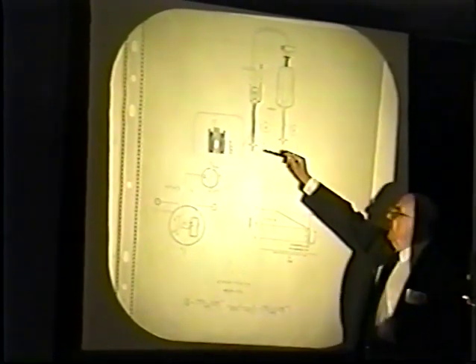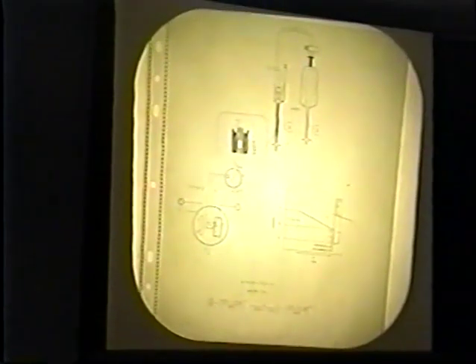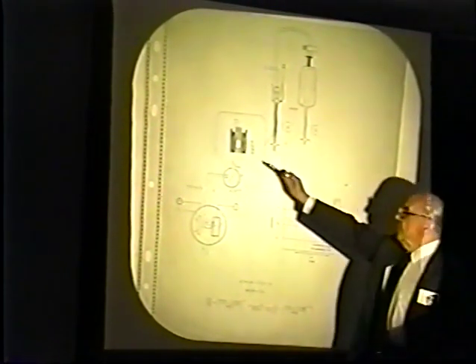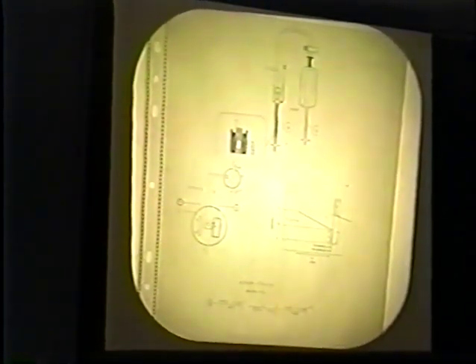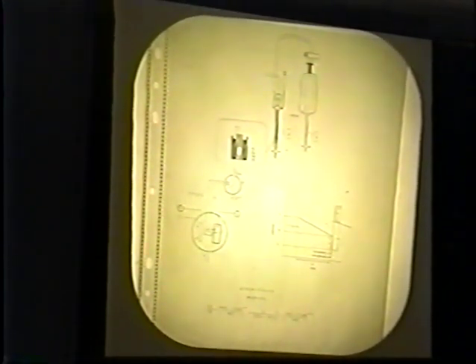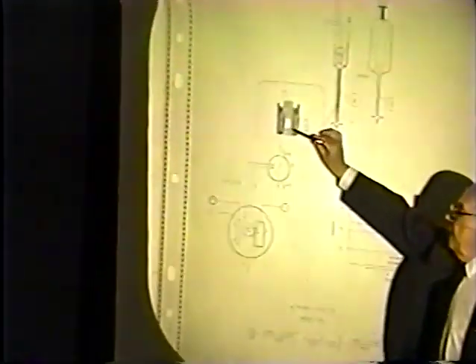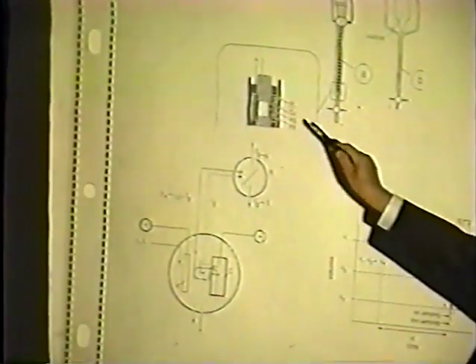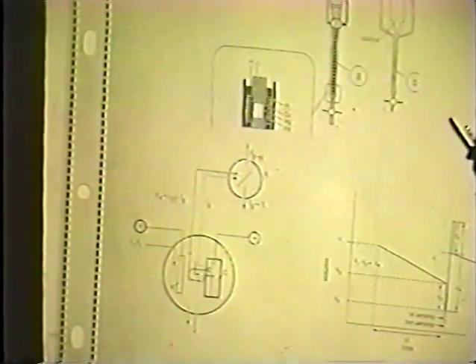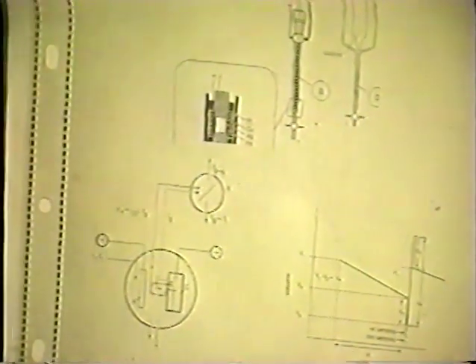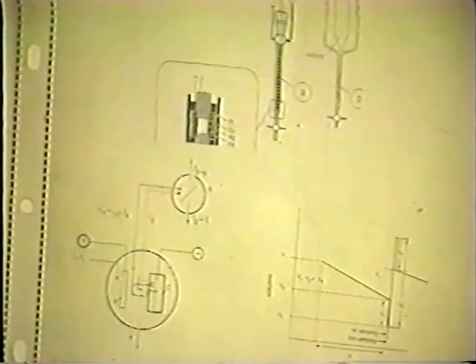Now, we constructed a cell which was essentially a very thin, calibrated part of a burette with the electrode design, which is given here. Essentially it was copper tubing, to which we plated first silver, then our palladium, and the counter electrode was a tightly coiled platinum. The cell was closed in the sense that a large surface catalyst was placed there, and again we could measure the volume of the recombined water.